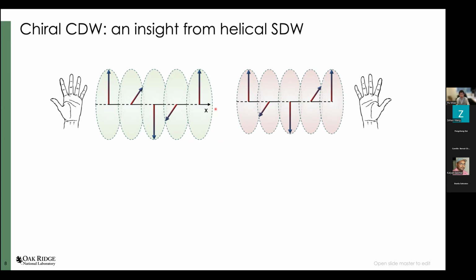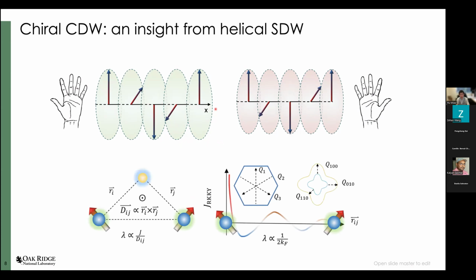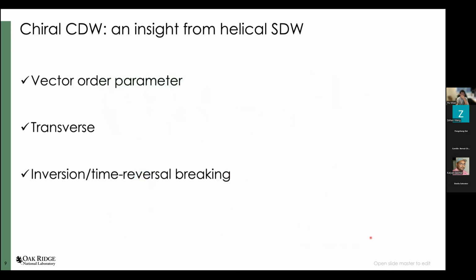In order to have this type of spin density wave, you either break the inversion symmetry to allow a DM interaction to give you a chiral spin texture, or you can have competing magnetic interactions, such as the J1-J2-J3 model that I'm drawing here. Then if you apply a magnetic field, you can select one chiral spin order over the other. With this, I think it's quite clear.